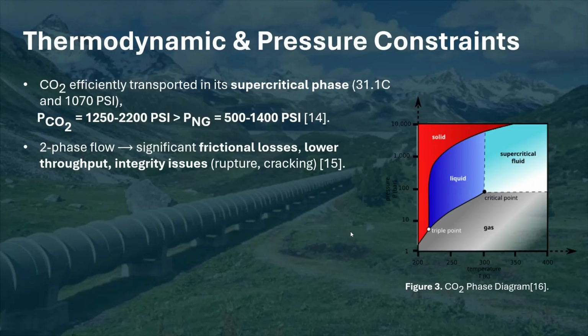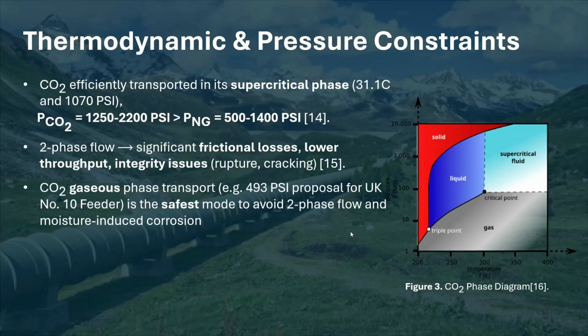Significant frictional losses from two-phase flow, lower throughput, as well as integrity issues such as rupture or cracking if specifically the internal pressure of the pipe exceeds the ultimate tensile strength of the steel. Then we start to see a lot of material-related issues.